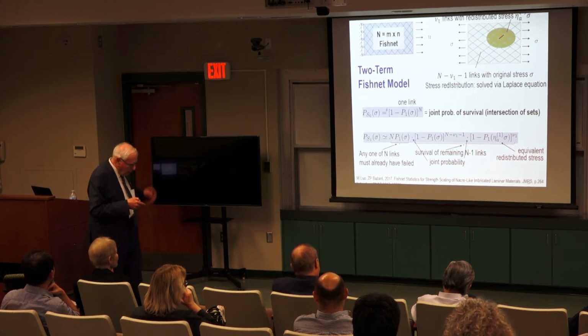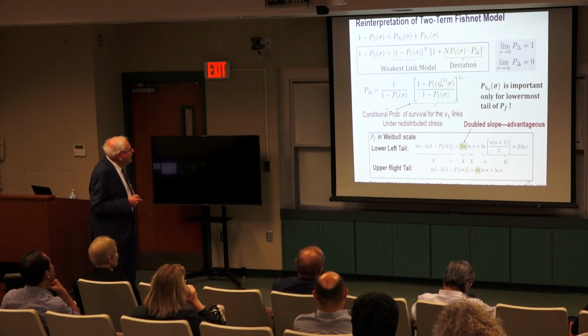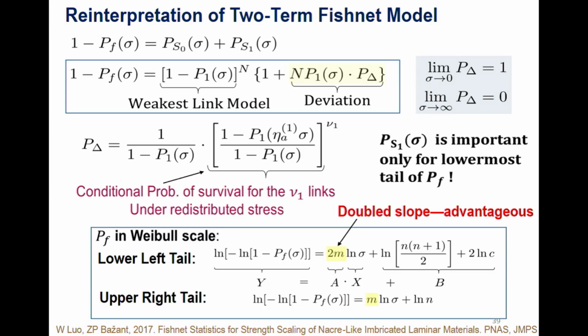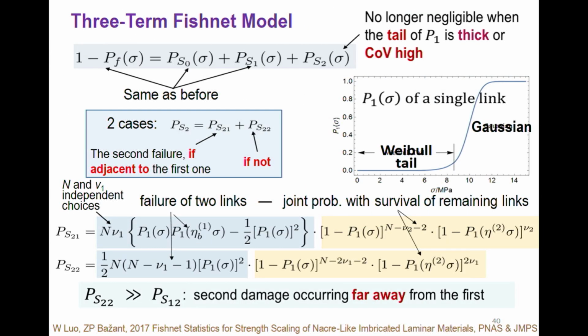So that's all calculated, and you can reinterpret it by putting it in the form of the Weibull distribution with a correction term. This is the correction term, which is easily calculated, and so that's a second order approximation, we'll say, with 2 terms.